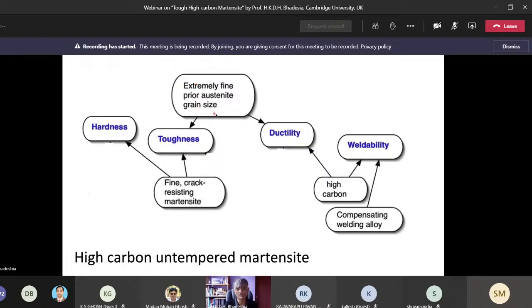So here is the flow chart for the design. We want to make an extremely fine austenite grain size. I'll come back to that later. I want the grain size to be of the order of 0.4 micrometers, okay? Really small. I need it to be hard because I want a strength which is of the order of 2 gigapascals, and therefore I'm going to design it with crack-resisting martensite, which hopefully has toughness, has ductility.